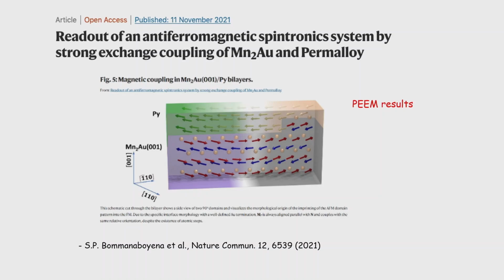a recent paper, and we see that they use TEM to look at the interface between manganese gold 001 and the permalloy, and they claim they have this very sharp interface, okay? And now we want to play with just one monolayer. It would be very nice to put one monolayer of iron 57, a very small layer of iron 57, and look again at this interface. We are trying to do that right now. Okay.